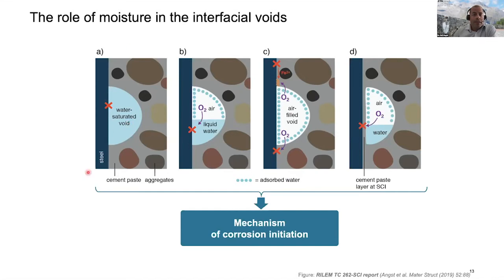So you can see these different cases here. On the left hand, we have a case where such an interfacial void is fully saturated with water. And in that case, we believe it's reasonable to assume that corrosion would start here within the void. But if we have a case where this void is not filled with water, but basically filled with gas phase and only has some adsorbed water molecules on the surface, we find it is very unlikely to get substantial localized corrosion under these conditions, because it is very unlikely to form a pronounced macrocell, a pronounced galvanic cell with the adjacent cathodic areas, because the adsorbed layer of water has a very high ohmic resistance compared to the concrete next to that void. So this in general reveals the importance of moisture and the degree of saturation exactly at the steel-concrete interface in triggering chloride-induced corrosion of steel in concrete.